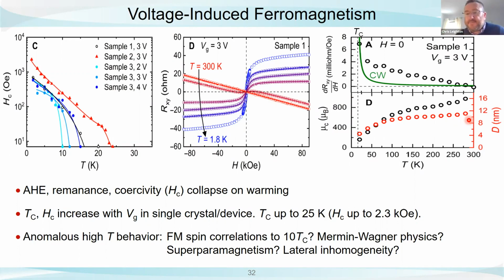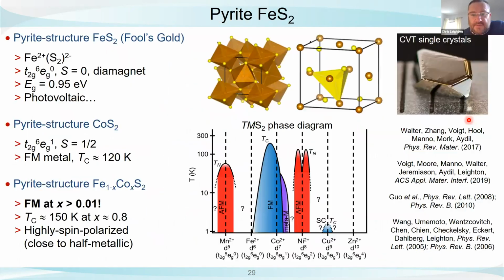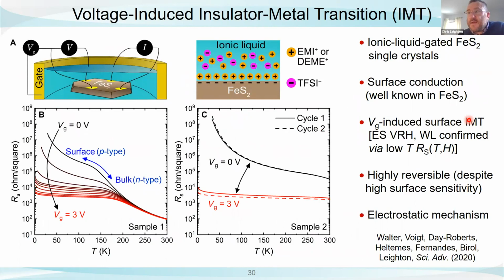Okay. Now, in the sulfide, you're asking a very good question there, because in the sulfide we found no such evidence. And why is that? It relates to the question that Xiaohong asked here, which is, it is a whole different ballgame for diffusivity for sulfur vacancies. It turns out that sulfur vacancy diffusivity in iron sulfide is extremely slow. So we believe that's critical here. Could we be forming sulfur vacancies in the very top unit cell? It's absolutely plausible, but they won't proliferate. They won't move any deeper because the sulfur vacancy diffusion rate is incredibly small. So we believe it's really that rate of diffusivity of the species that can be made that controls whether you get a broadly electrochemical or electrostatic response.